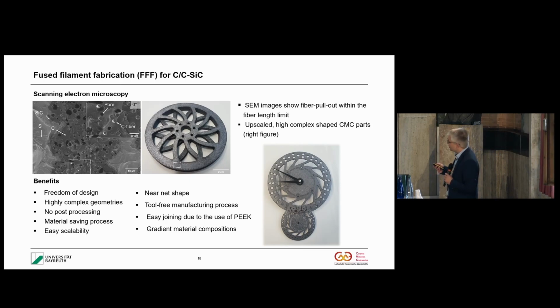Even so, these commercial fibers had a fiber length of about 500 microns. Even there, you already see some kind of small pull out, but nevertheless, 500 microns, as everyone knows in this field, is not sufficient as the fiber length.